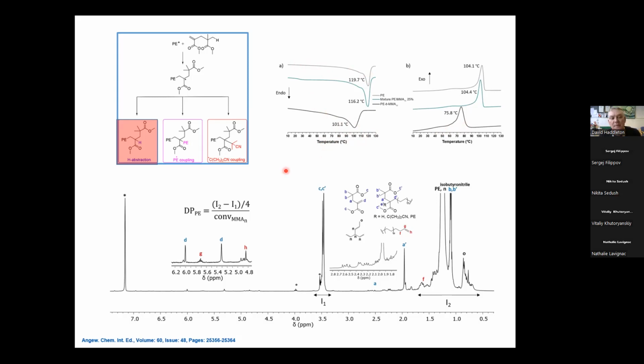The NMR, and again, the NMR can be quite detailed, but that's where Lyon are experts at looking at the carbon-13 NMR of polyethylene and branched polyethylene, and so they were very happy to be able to assign these D peaks as these peaks here in the middle of the molecule.